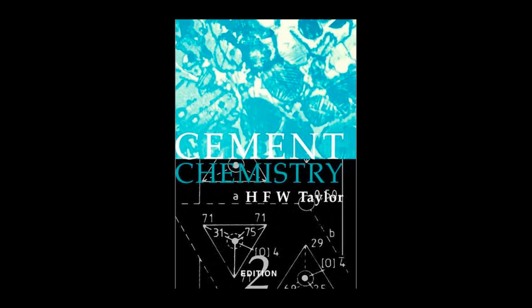Their hydraulic activity comes primarily from monocalcium aluminate, CA. They set very fast and are highly resistant to sulfate attack in dilute acids, provided the pH stays above about 4. They're often used in refractory concrete or in sewers. But they have that famous conversion issue that led to some high-profile structural failures decades ago. Yes, the strength loss associated with conversion is the main drawback.